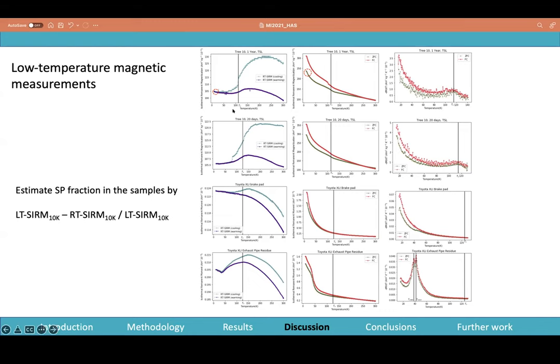curve. So two things to notice, the key takeaway over here. One is that the zero field cooling curve of the LTSIRM was always lower than the field cooling curve. So broadly, our samples were mostly dominated by single domain grains. Another thing to notice, in two of these tree leaf samples in particular, this is a 1 year exposed leaf sample, you can see a humped shape, which has been attributed by Özdemir and Dunlop in their 2010 paper to being characteristic of surface oxidized magnetite. And you can also see how the Verwey transition is normally at 120, but we observed it at lower temperatures, which also supports the idea that most of our magnetite-like particles were surface oxidized.